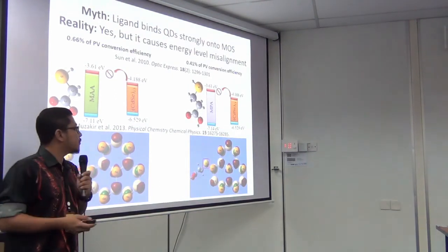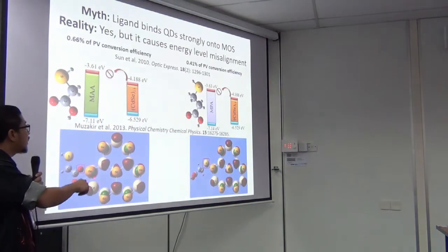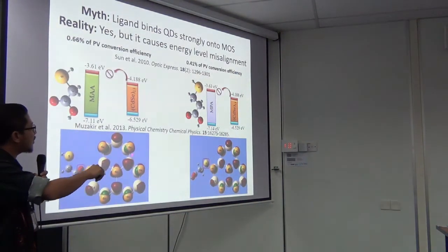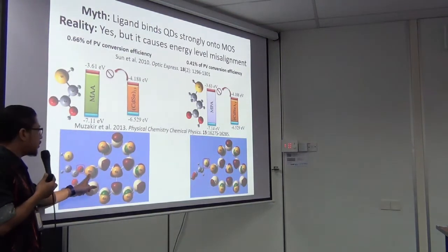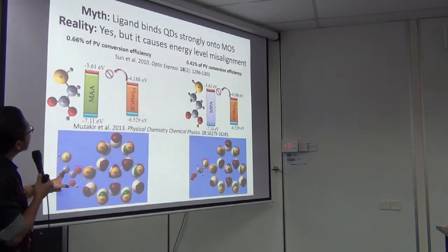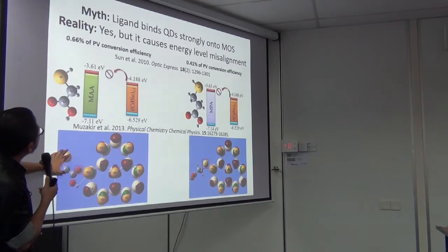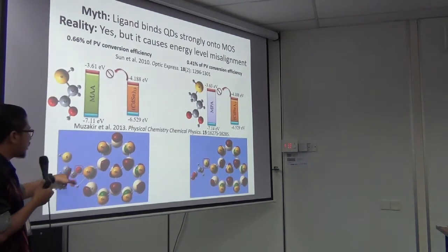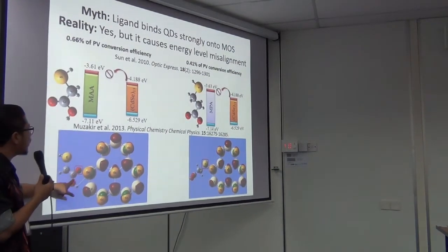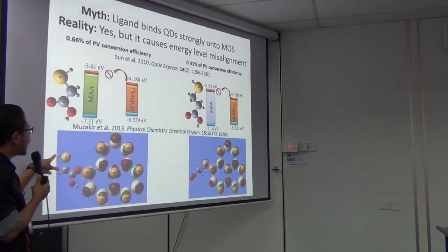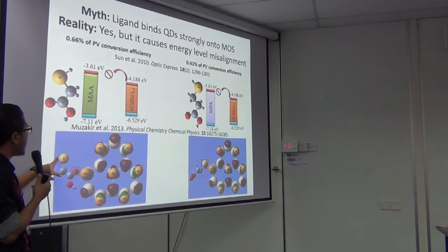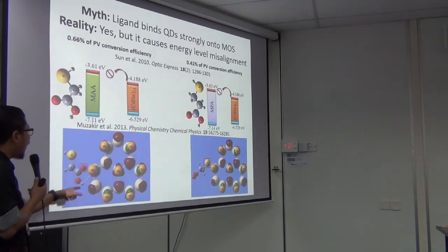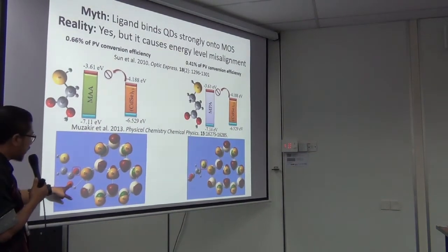This is an example. This is our quantum dot, the CdSe, the best performing CdSe, which is CdSe 13. And we attach our quantum dot with a ligand, and this ligand is, let me see, mercaptoacetic acid. This is the structure of mercaptoacetic acid. We have the mercaptan functional group over here, SH is mercaptan, and we have COOH over here, carboxylic.